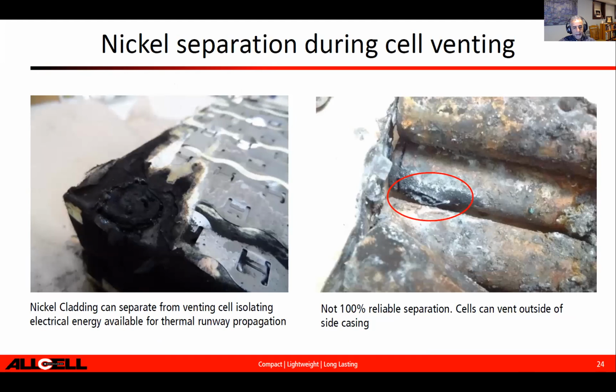Here are pictures of the autopsy of the module. What's interesting here, I want to point out a couple of things that we discovered that are critical. One to the left, we found that the nickel cladding, or the current collectors on the top, actually play a significant factor in providing safety in the pack. The reason is when one cell has failed, it becomes a short circuit, and the other cells start dumping current into it, which causes a significant amount of heating because of ohmic heating from the rush current that passes through those cells.